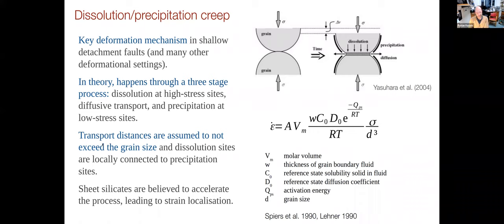Okay, so transport distances are assumed not to exceed the grain size. And dissolution sites are locally connected to precipitation sites. The other thing that's important, many of you will have seen if you looked at a stylolite in the field, a stylolite is essentially localized pressure solution. Stylolites are these wiggly patterns you often see in limestones. Actually, most of what's interpreted as bedding planes in the basal quartzite are actually stylolites.